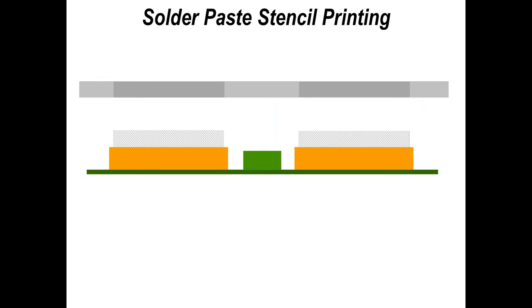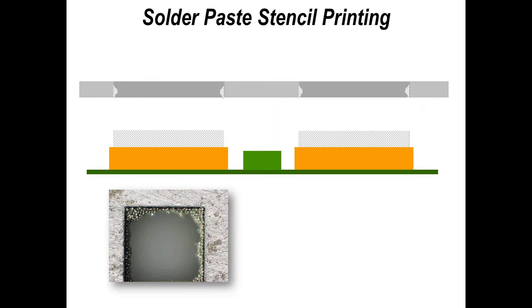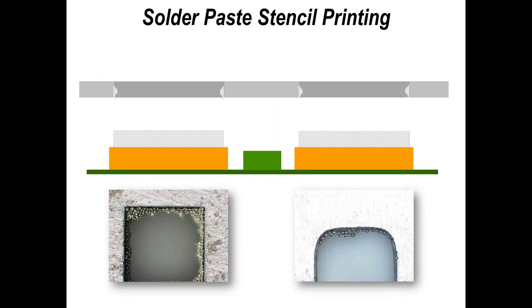So consequently, that force is pulling it out. If any material is left within the aperture of the stencil, then perhaps it's a stencil issue. It's a design issue because the stencil wall surface area is larger than the pad we're printing onto, or perhaps the printing parameters are not set up correctly. Each one of those needs to be investigated.